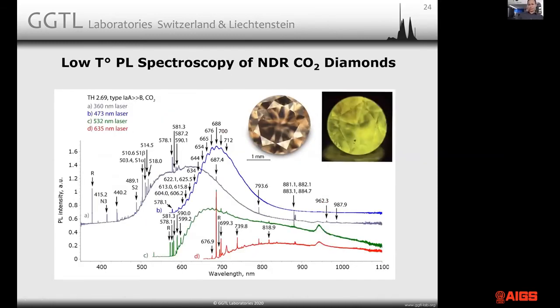Here is the fluorescence of such a stone. So this is the PL spectroscopy. The most interesting band in here is that wiggly band centered at about 690 nanometers. This band is known from many oxygen-containing diamonds, from those typical orange, yellow, so-called 480 nanometer diamonds. They contain this band. There are lots of nickel-related features in these spectra. The yellow fluorescence that you see visually comes very likely from the S1 and S2 center absorption, which you can see in trace A on the left side. So that's what the yellow fluorescence originates from.